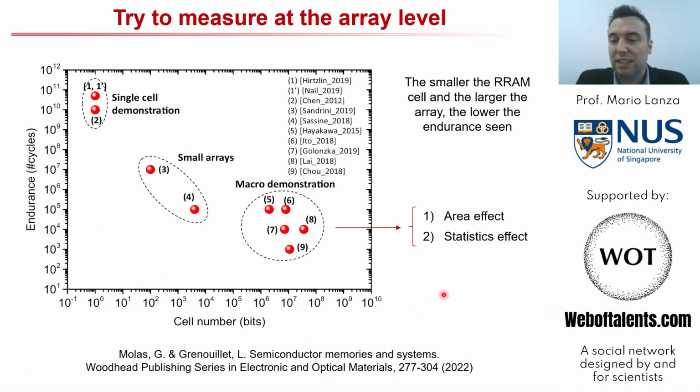There is another interesting study that has compared what is the endurance claimed for those works that analyze just one single big device and for those studies that make an array with small devices. And you can see that the differences in endurance are huge. So we always recommend to study devices that are as small as possible and integrated in the microchip.